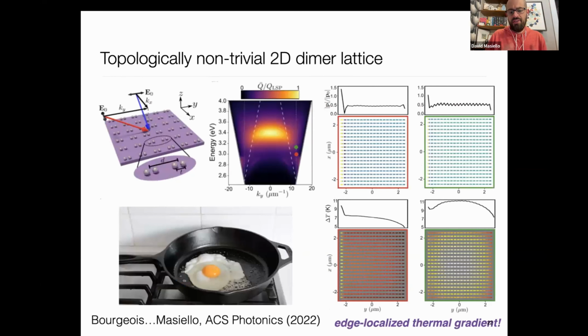And so my very last slide here extends this to 2D, and things are a lot more complicated in 2D. But maybe if you just focus down here on these bottom panels, we're just exciting the lattice at two different energies or frequencies at the X point, and I'm showing you the thermal gradient rise that clings to the edge that you see down here, and it falls off back to room temperature or closer to room temperature in the bulk. And this is extremely unusual, and I have this kind of silly picture here because this is not at all how we experience temperature. We know when we cook our food, for example, we put the pan on the stove and the entire pan heats up. What I'm telling you here is that, at least theoretically, what we're predicting is the existence of materials that heat up on the outside, but the middle where you cook your food remains cooler.